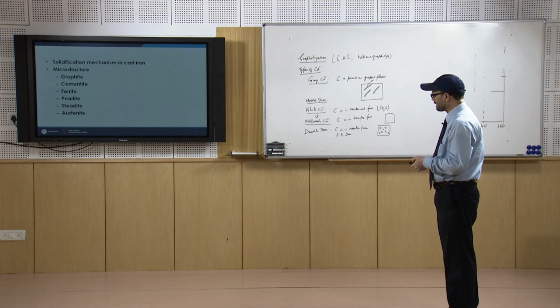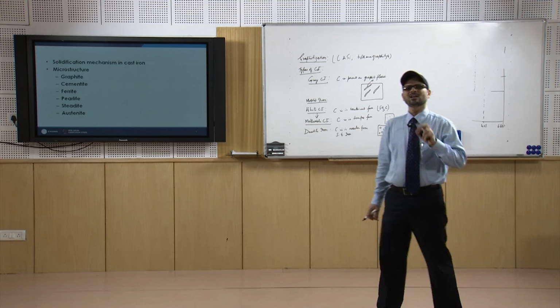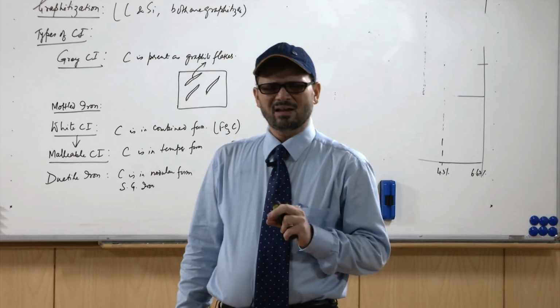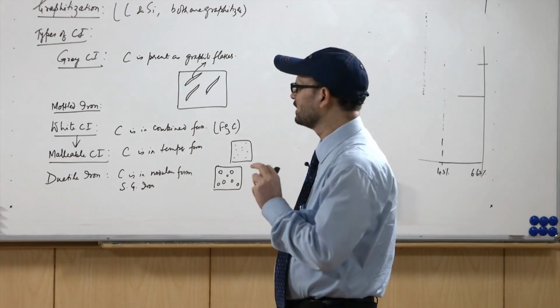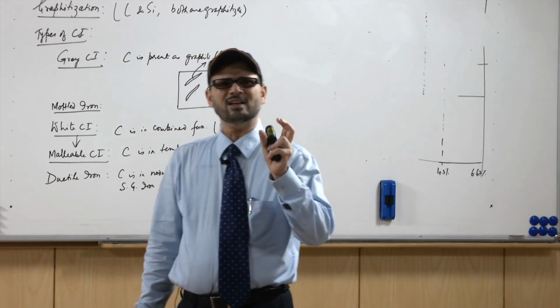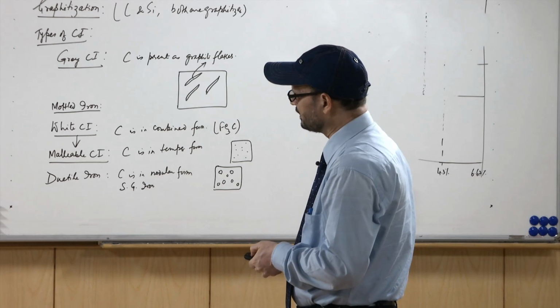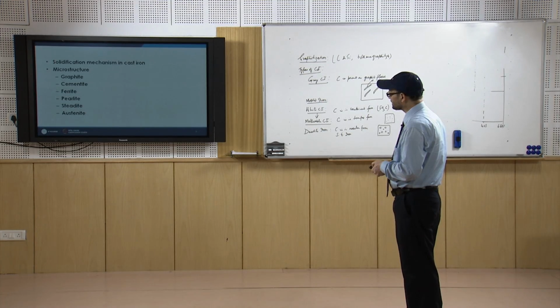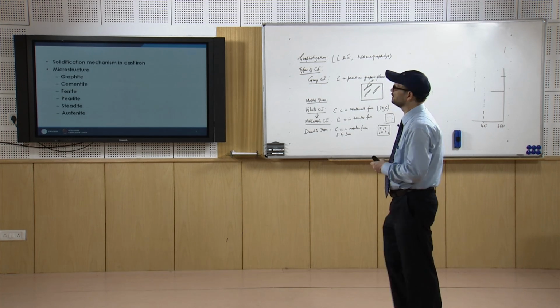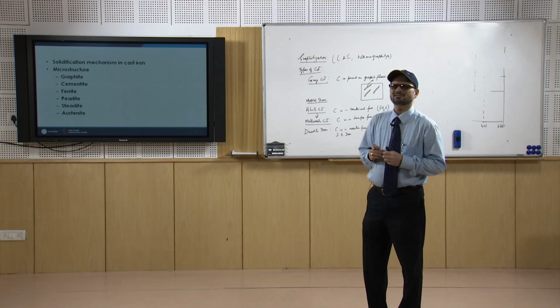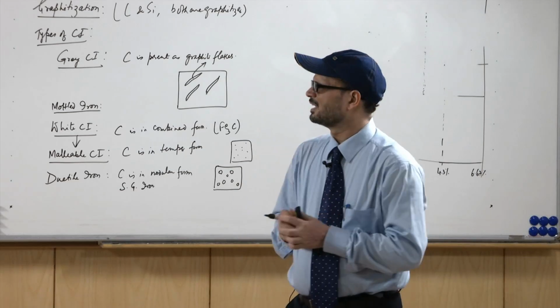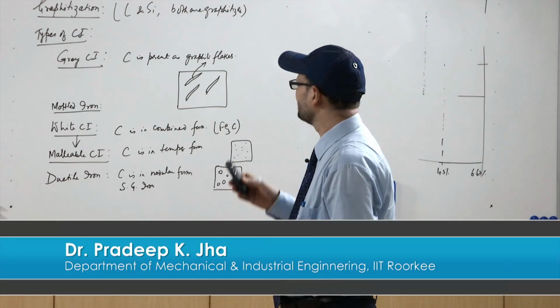Austenite, as we know, is otherwise not a stable phase at room temperature, but if we add nickel as the chief alloying element to a larger extent, then nickel being an austenite stabilizer, you also get the austenitic phase in that cast iron. So, depending upon the conditions, you may have the formation of these different phases, different kinds of matrices, and you may get different varieties of cast iron. They are grey, mottled, white, malleable or ductile iron.